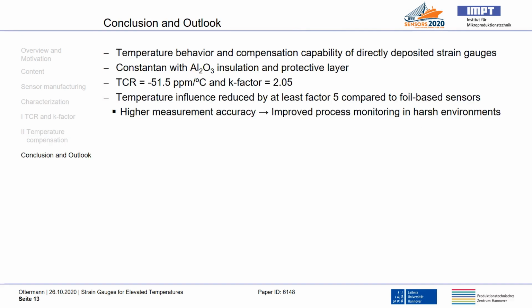With these outstanding results, I would like to give you the conclusion and the outlook of our work. I have shown you the temperature behavior and the compensation capability of directly deposited strain gauges with a new coating system. Therefore, we used a layer stack consisting of constantan with an alumina insulation layer and an alumina protective layer on top of the sensor layer. The results for the single strain gauges were a TCR value of minus 51.5 parts per million per degree Celsius and a K-factor of 2.05, which was independent from the temperature.